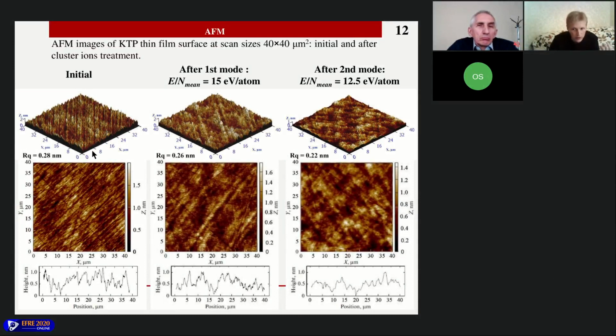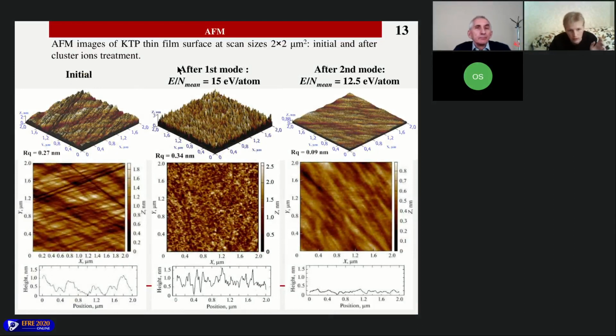You see traces of preliminary mechanochemical polishing, and after treatment, we smooth the surface. And at the small scales, 2 by 2 micrometers, we see the greatest decrease in roughness, by 3 times. Here we see that the high energy mode removes scratches and traces of mechanochemical polishing, but it significantly degrades the surface profile and increases roughness. But after the second mode, the heights of the surface profile significantly decreased.